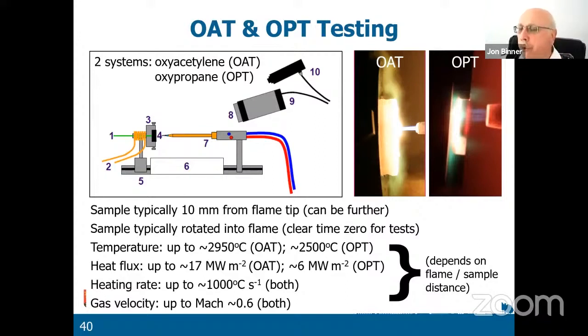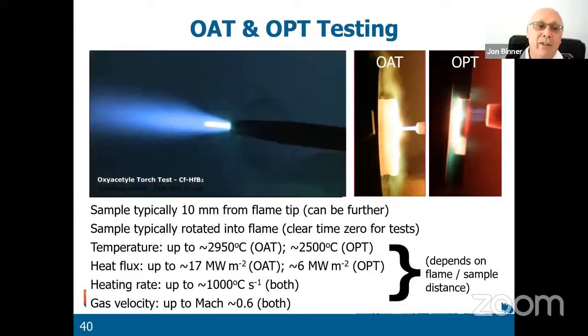The oxypropane torch is multiple flames. And this is the oxyacetylene torch test. It's been edited. It was a 5-minute test. We've edited it down to a few seconds. There is the sample coming in. You can see the heating rate.